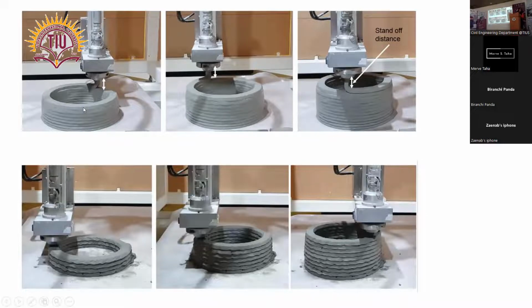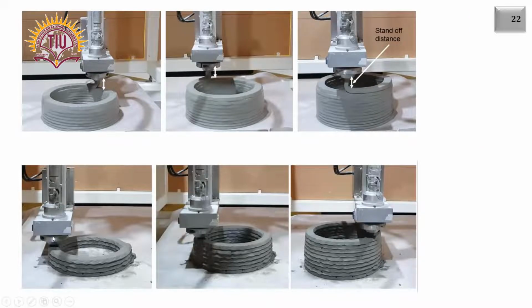You can see that this is an old geopolymer, and we modified it using some chemical admixtures, and you can see that there is no deformation during printing of the same design. Previously it was slumping. You can see there is an indication of stand-off distance. It means if you print slowly, the entire structure is going to collapse.